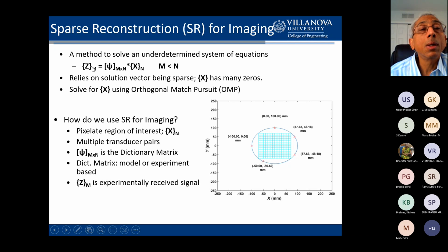Now, what is my z vector, which is the left-hand side over here? Well, that's the signal I get when I activate one of these transducers and let it send a guided wave through this region, interact with whatever is here, defects, etc., and then arrive at my receiving transducers. There are 4 of them. I can activate each transducer in turn and receive at all other 4 transducers. So basically I have 5 times 4, 20 signals that I can get effectively. Those 20 signals constitute my Z vector.